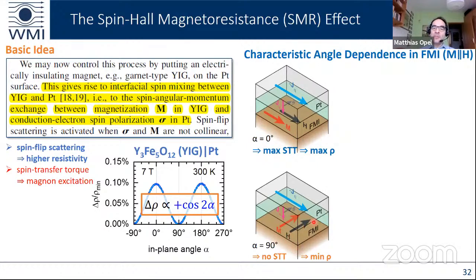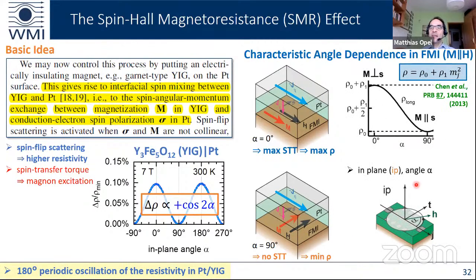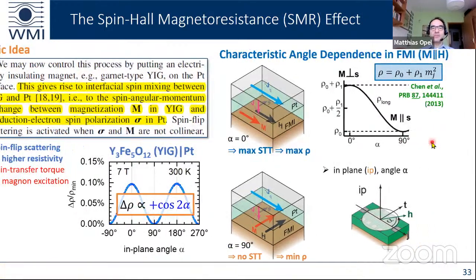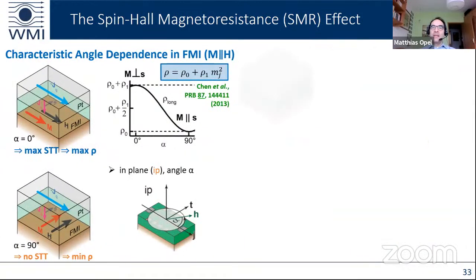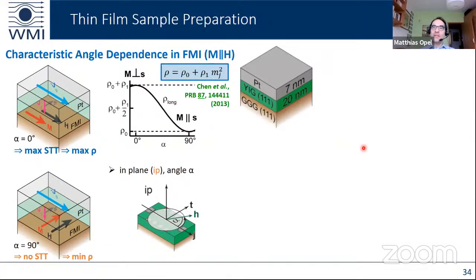If we rotate the magnetic field by 90 degrees, M and S are parallel. We have no spin transfer torque at the interface and the minimum resistivity. And this is shown here. Maximum resistivity at 0 degrees in our coordinate system, minimum resistivity at 90 degrees. And this leads to this characteristic oscillation.